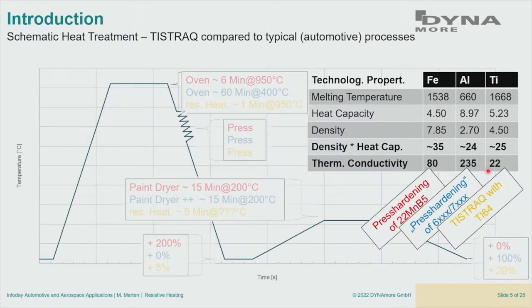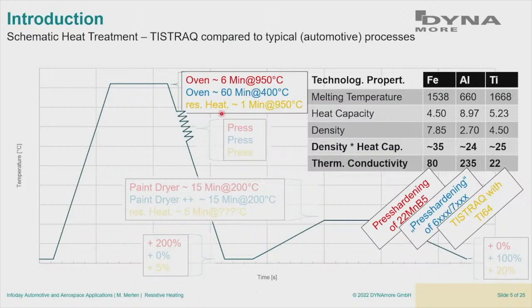If you have a wrong temperature in aluminum, due to high thermal conductivity the temperature will equalize to the neighboring region. But in titanium it will take much longer, making processes more difficult. Looking at process parameters, we have different temperature and time schemes. For aluminum it depends on the alloy — there are several compositions with several heat treatment paths. Steel and titanium are in a similar temperature range, but in terms of time we are aiming at a much shorter process duration.